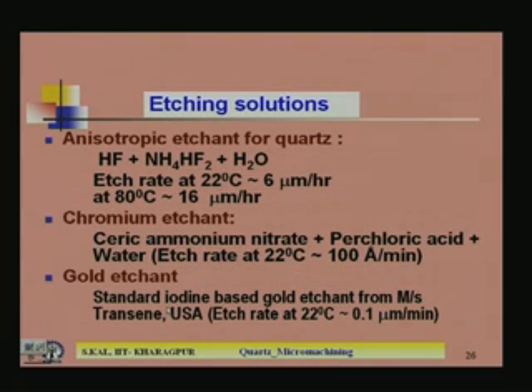Then for gold etchant we use a standard iodine based gold etchant from Transene, USA, that is one supplier who can supply a lot of chemicals which are used in etching of different kinds of materials. So, we have procured that iodine based gold etchant, and its etch rate at room temperature is 0.1 micrometer per minute. So, these are the etching solutions for masking material as well as quartz, which have been standardized in IIT Kharagpur, the quartz micromachining laboratory. Okay.